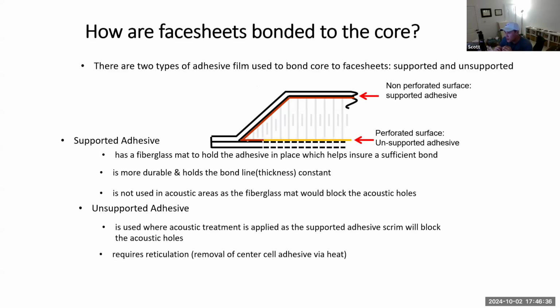It is not used in acoustic areas as the fiberglass mat would block the acoustic holes, which is not what you want. So on the perforated skin side, what they typically use is the unsupported adhesive, which is adhesive without the fiberglass mat. So it is used where the acoustic treatment is applied, as the supported adhesive scrim will block the acoustic holes, as I mentioned. It requires reticulation, removal of center cell adhesive via heat. So as you can see here, this red line is the non-perforated surface, and it's using a supported adhesive, whereas this bottom region here is the perforated surface, and it's using the unsupported adhesive to bond the face sheet to the core.